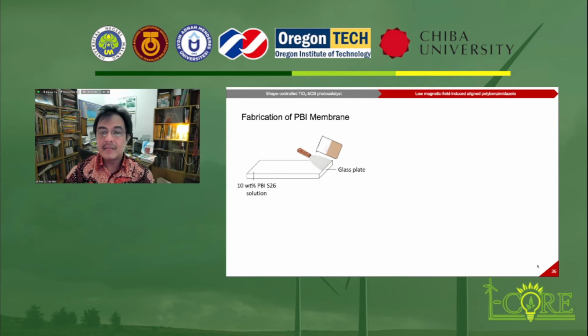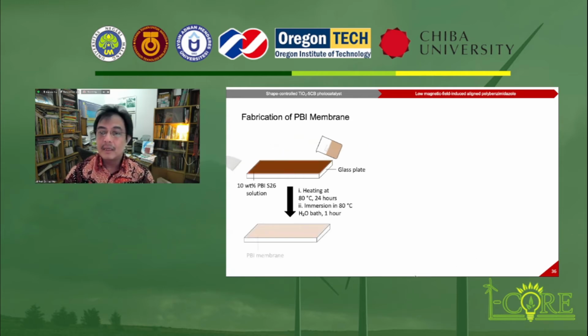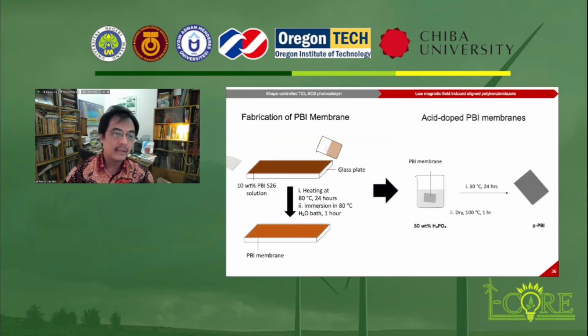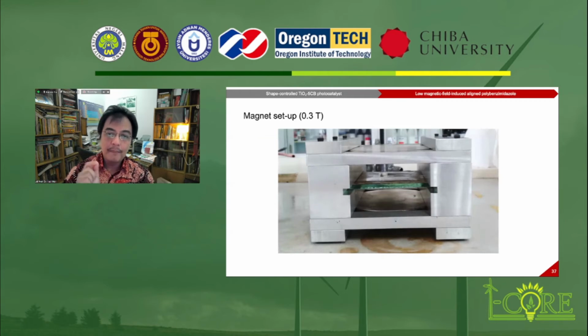Fabrication of polybenzimidazole is done by casting, followed by doping using phosphoric acid. It is a very simple method. And we use a homemade magnet whose magnetic strength is 0.3 Tesla. The sample is placed between the north and south poles of the magnet, so that it is expected that the polybenzimidazole membrane can align with the magnetic field.